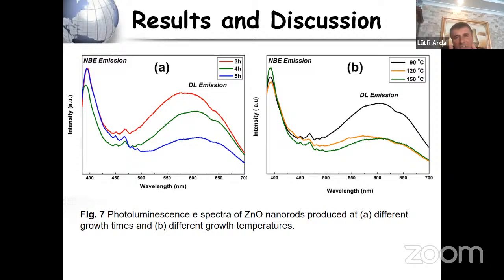Besides, a few peaks were observed between 450 nanometers and 500 nanometers, look at these few peaks, which came from the use of the xenon lamp. In the UV region, a sharp transition peak corresponding to near band edge emission was observed at around 392 to 395 nanometers for zinc oxide nanorods. This emission in the UV region generally was attributed to the near band edge transition, a common optical property of wide band gap zinc oxide.